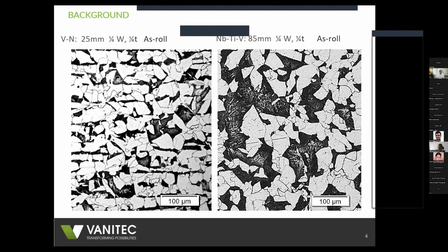Well, not only is it mixed, but it's coarse and mixed on conventional rolling, which makes it particularly dangerous and forces you to do a subsequent treatment. You know, so as shown here, and you're right, Dave, the diffusion. I mean, niobium atomic mass is 92 gram per mole, whereas the vanadium is almost half that, 51, isn't it? So you would expect it to be more sluggish in its diffusion rate. Yeah, and I would imagine, I can't remember the diffusivity of the two elements. Yeah.